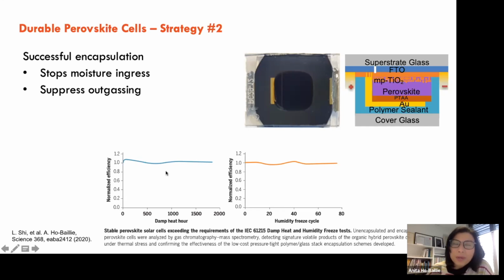The industry standard is 1,000 hours, and our cells are able to last for 1,700. We also put them through thermal cycling and a humidity freeze cycle. So we freeze them rapidly. What it means is that if there's any moisture going into the cell, when you freeze them, it forms little ice crystals, and they can wreck the encapsulation and the packaging.